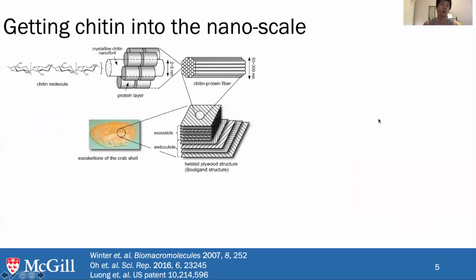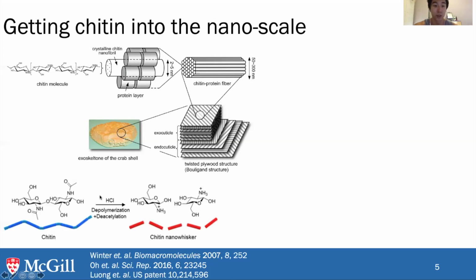There's been a lot of work in getting chitin into the nanoscale. We can see here that it exists similar to cellulose in trees, where we have the exoskeleton of crab and the chitin embedded in a matrix of protein fiber. It layers itself in this Bouligand structure, or twisted plywood structure, which is similar to that of a cholesteric order of liquid crystals. How you can extract it is similar: you use acid hydrolysis to get rid of the amorphous regions of chitin, and you're left with these chitin nanowhiskers or nanocrystals